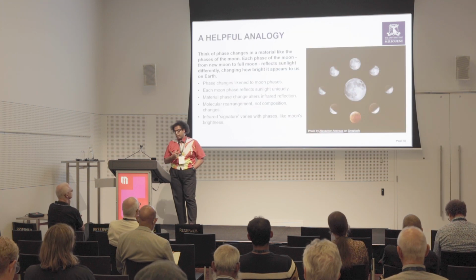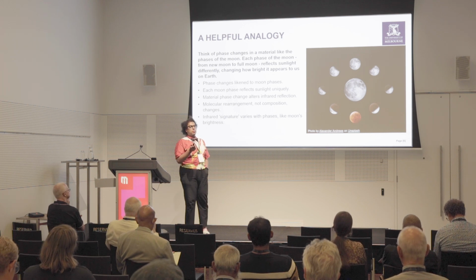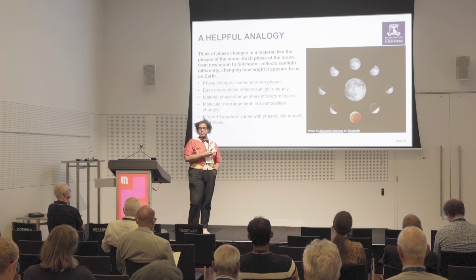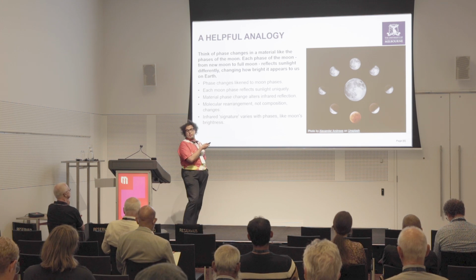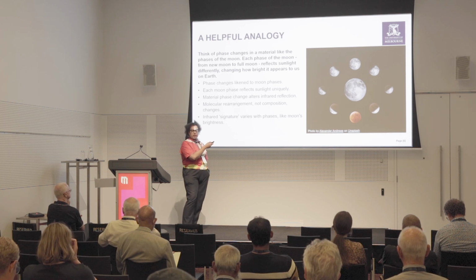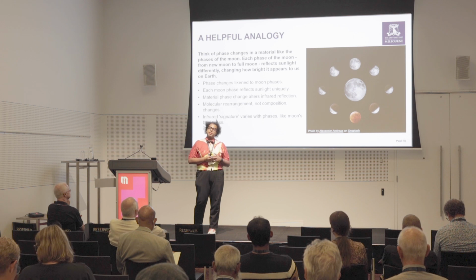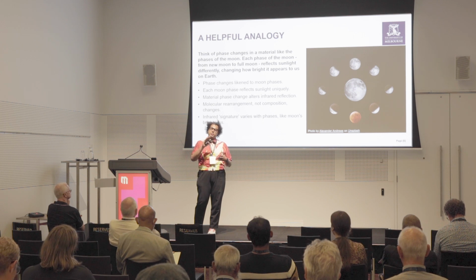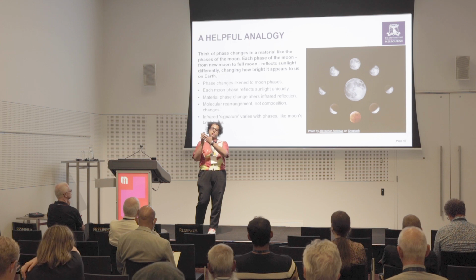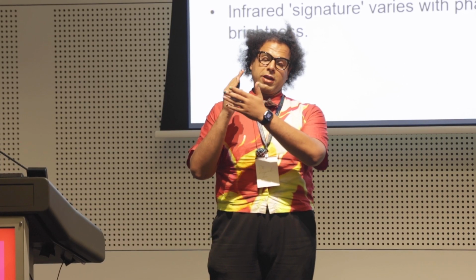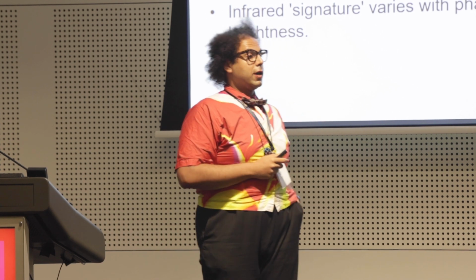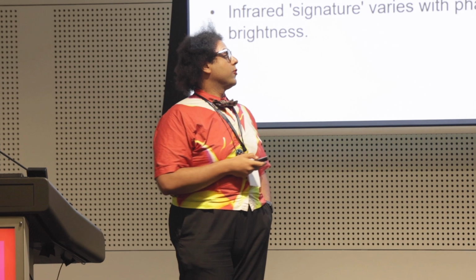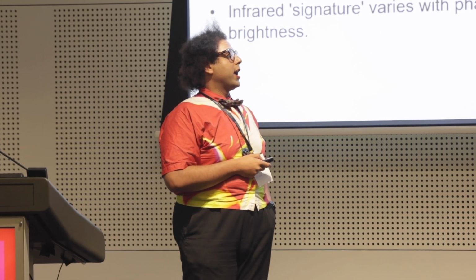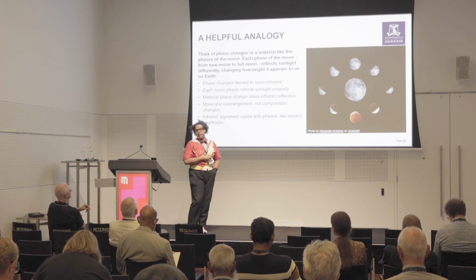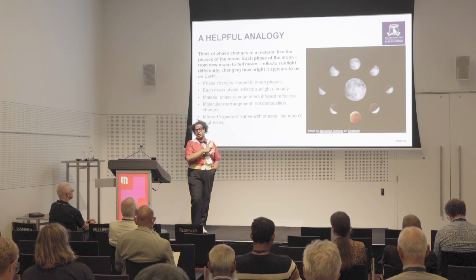This analogy is how I think of vanadium oxide. It's similar to the moon. It has many phases, and what we see is what's reflected. So every stage of the month is a different stage. The moon remains the same. So in a similar sense, vanadium oxide is still vanadium oxide, but as you apply the stress or the triggers, it starts to shift and move, and that reflectance changes, both from an electronic point of view and from an optical point of view. We only say insulator and metal because it is a big change, say, between a crescent and a full moon. But throughout that change, there are so many things changing at the same time.